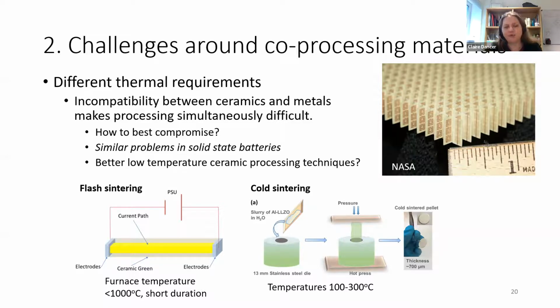dense sample, very nice, or cold sintering, which is a really new method where you can use a different type of densification mechanism to densify at really low temperatures. So there are ways that we can start to come around some of these things, but partly the problem here is knowing about them, knowing people who can do them and knowing people who can help you with them.